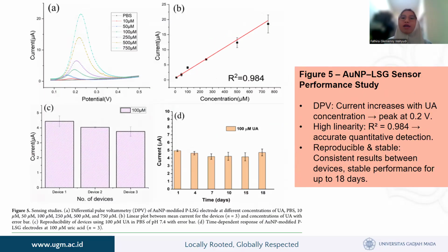This is about figure 5, AuNP LSG sensor performance study. We go from 5A, differential pulse voltammetry or DPV graph of AuNP modified PLSG electrode at various uric acid concentrations from 10 until 750 micromolar. An increase in peak current is observed as the UA concentration increases. The peak occurs at around 0.2 volt, indicating the oxidation reaction of UA on the electrode surface. So the linear graph between peak current versus UA concentration shows a strong linear relationship. The R square is 0.984, indicating the sensor ability to detect UA quantitatively and accurately.